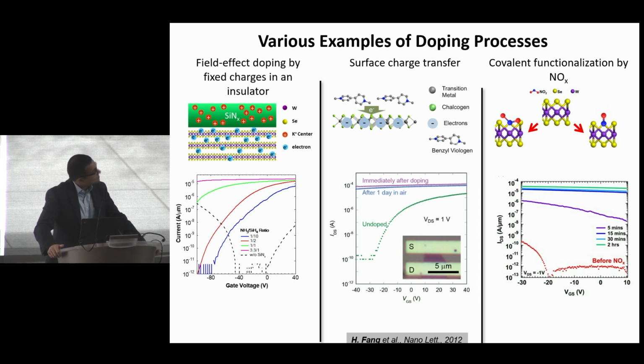So the question is, how do you do remote doping? And the very first works that we did in this field, looking at the 2D devices, going back to over 10 years ago, was looking at doping, and specifically doping in the context of contacts. And in fact, at the time, the only monolayer semiconductor that was shown to have high mobility was molybdenum disulfide. People had tried to make tungsten diselenide monolayer devices. The mobility was very low.